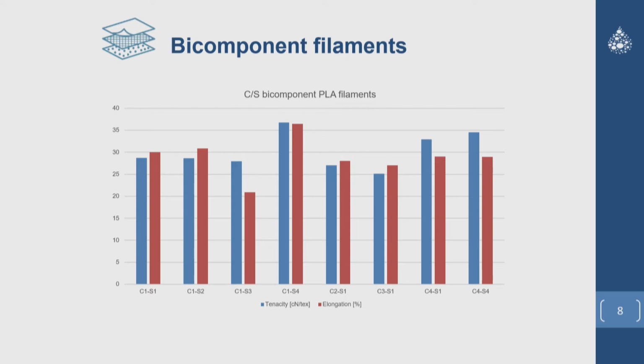So you see that the combination of core 1 with sheet number 4 results in the best tenacity and the best elongation. But I want to have some special attention to the third combination. Here we tried using a semicrystalline PLA grade, both for the reinforcement and for the matrix.